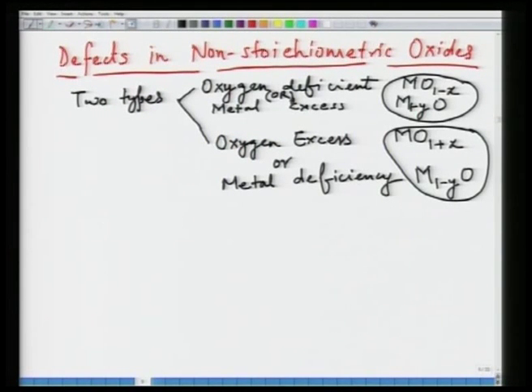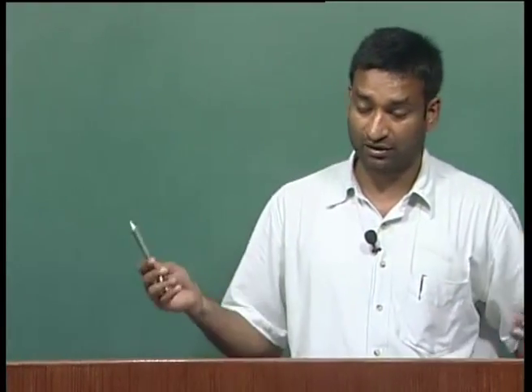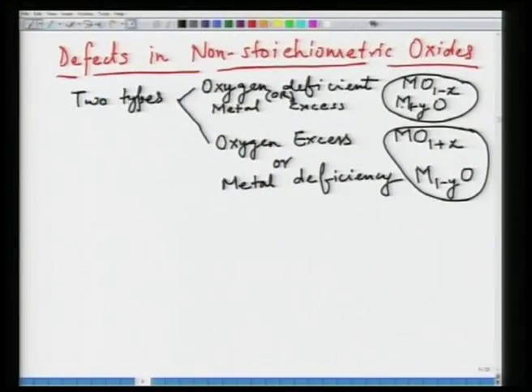And then we looked at defects in the non-stoichiometric solids. In reality, what happens is that most of these materials operate either at high oxygen pressure or low oxygen pressure, and depending upon the operating conditions, they are often non-stoichiometric. So there are two basic types. One is oxygen deficient or metal excess, which is denoted as MO1 minus X or M1 plus YO. And second type is oxygen excess or metal deficient, and this is written as either MO1 plus X or M1 minus YO.